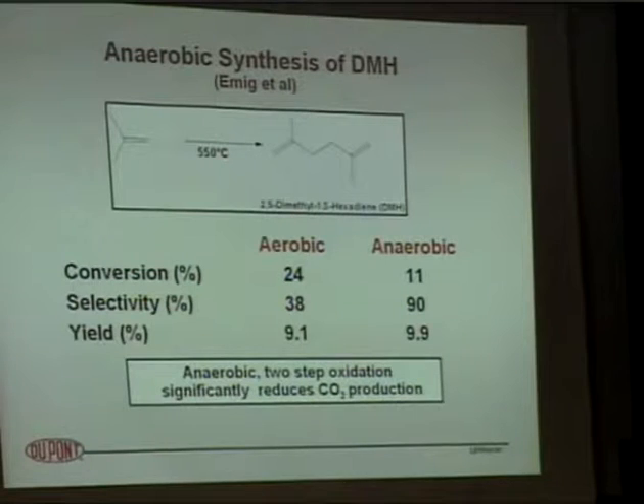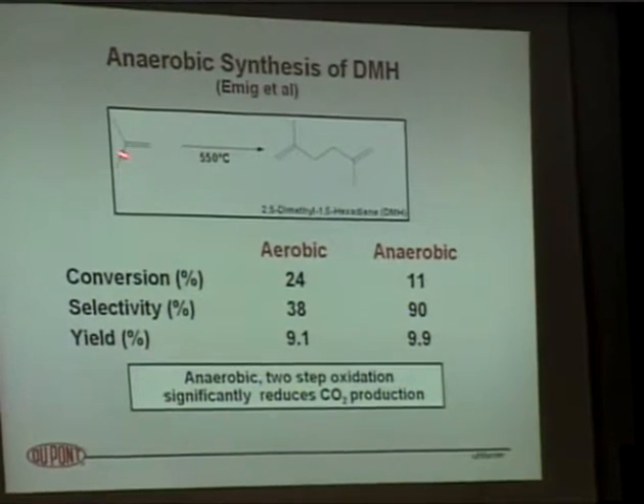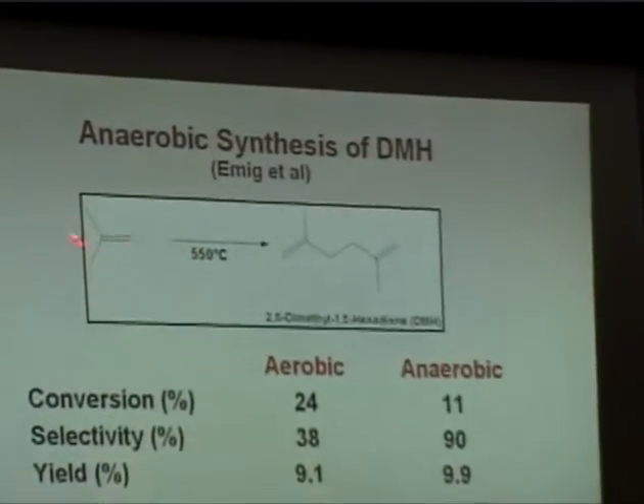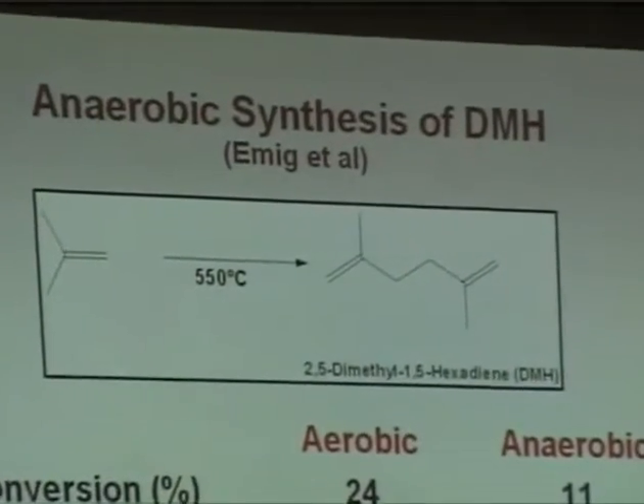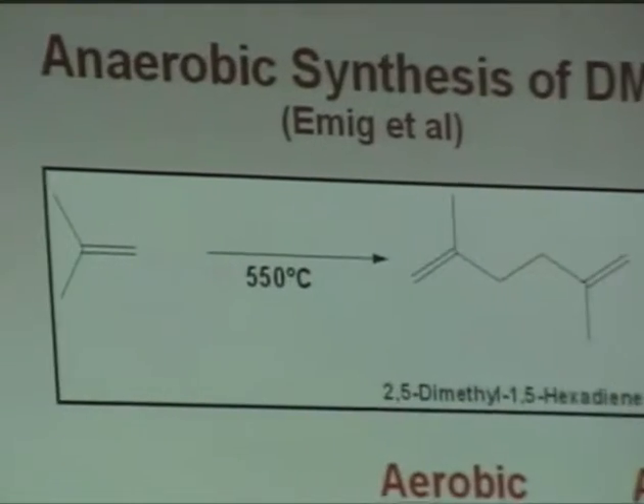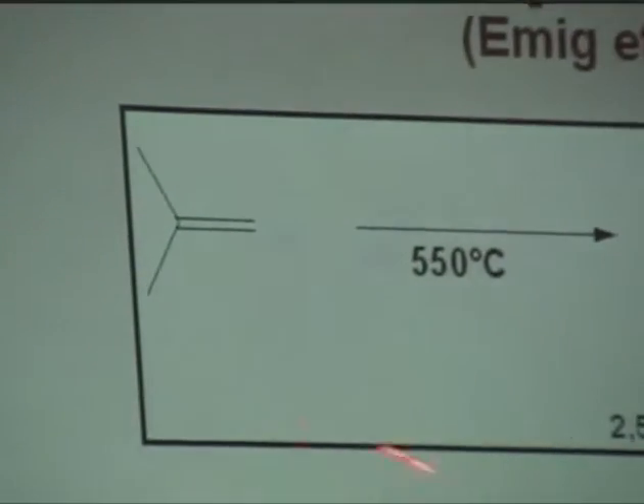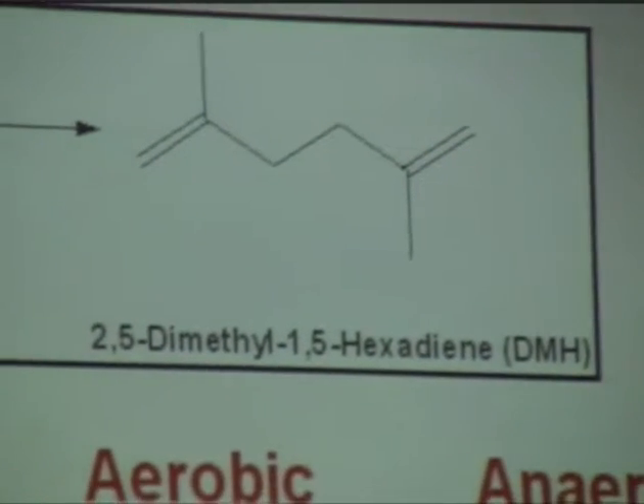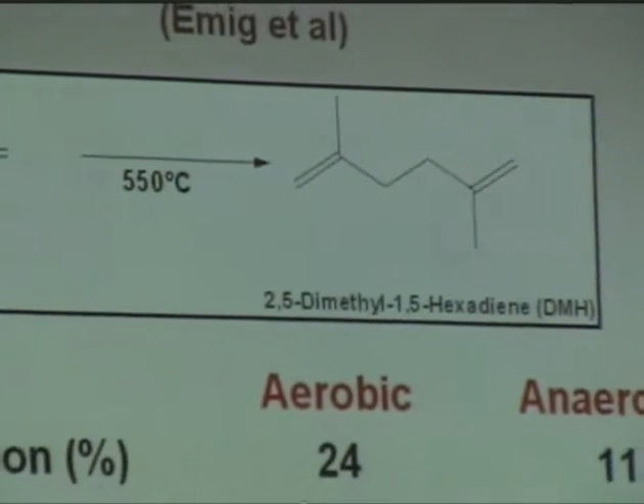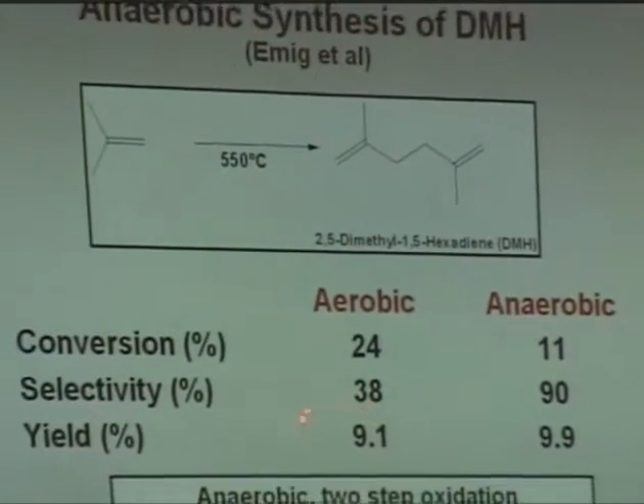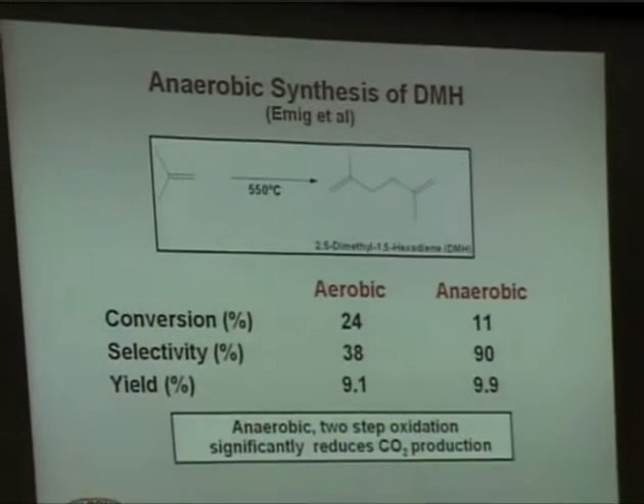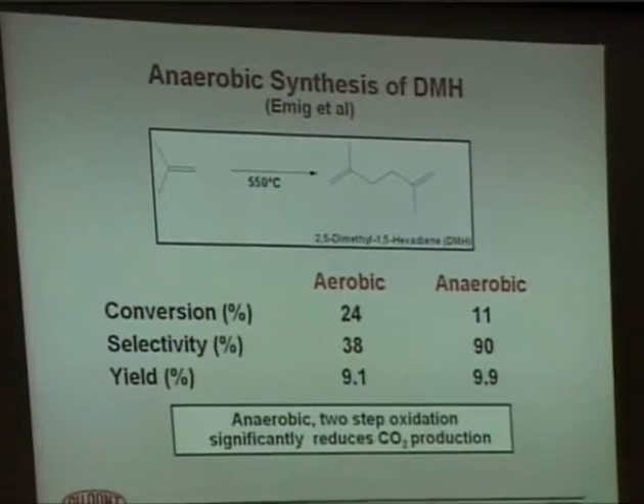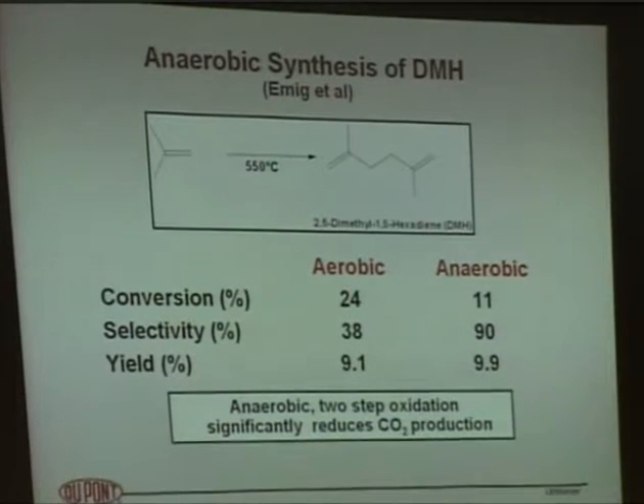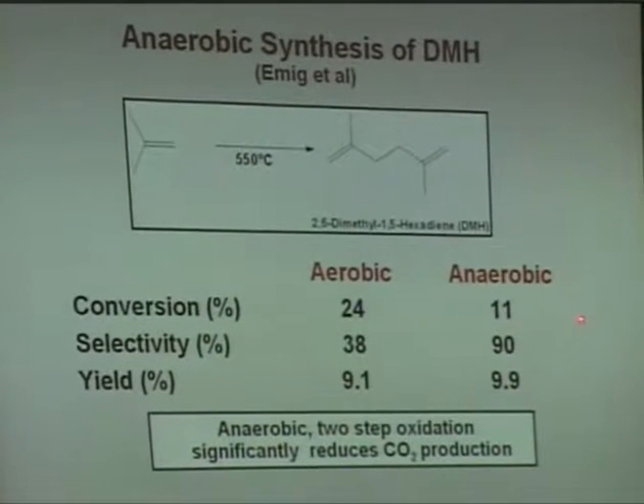I think probably one of the most striking examples I could find was this report by Emig of Germany, who was looking at the oxidative dimerization of isobutylene to this dimethylhexadiene, which goes into certain specialty chemical applications. In the aerobic mode, where you're feeding air to do the dimerization, conversion 24%, selectivity was very low at 38%, coming up with a 9% yield in this process. Now, by leaving the air out of the reaction, doing it strictly in an anaerobic mode with the catalyst that he was using, look at the big difference.